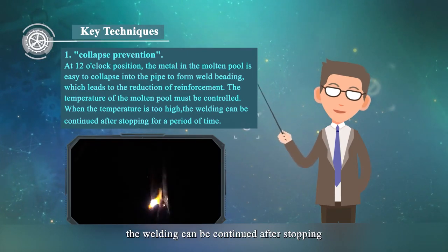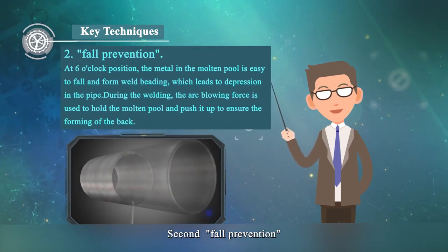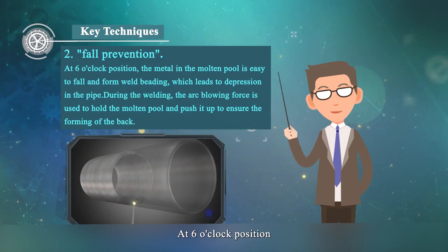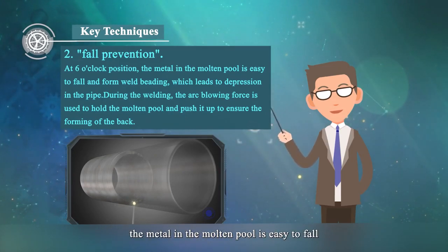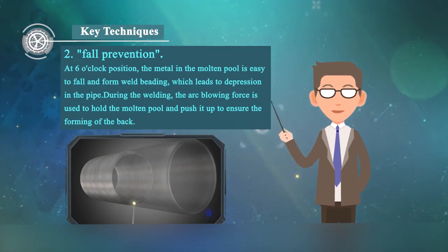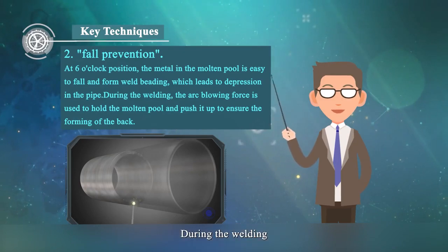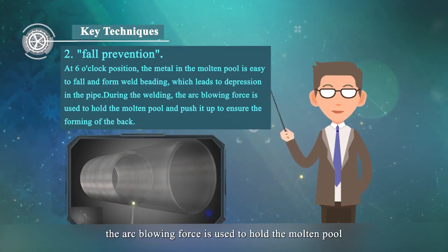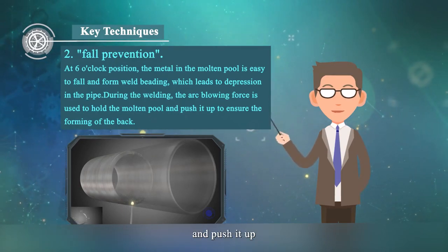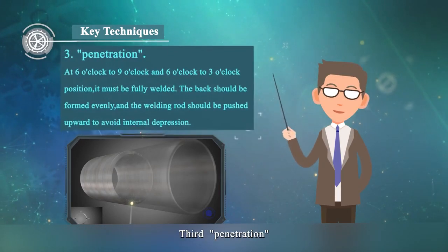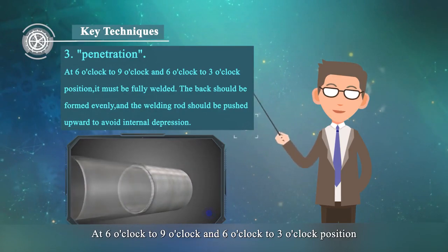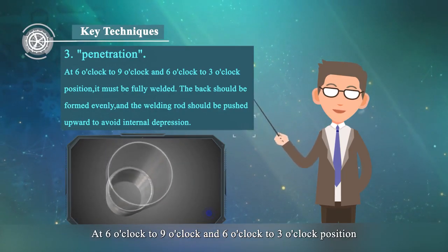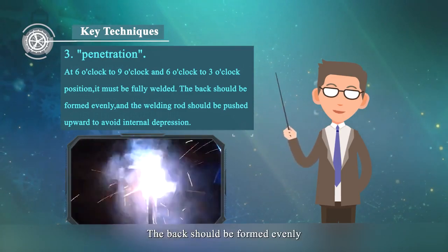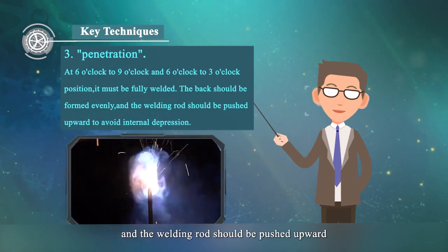When the temperature is too high, the welding can be continued after stopping for a period of time. Second, fall prevention. At 6 o'clock position, the metal in the molten pool is easy to fall and form weld beads, which leads to depression in the pipe. During the welding, the arc blowing force is used to hold the molten pool and push it up to ensure the forming of the back. Third, penetration. At 6 o'clock to 9 o'clock and 6 o'clock to 3 o'clock position, it must be fully welded. The bead should be formed evenly and the welding rod should be pushed upward to avoid internal depression.